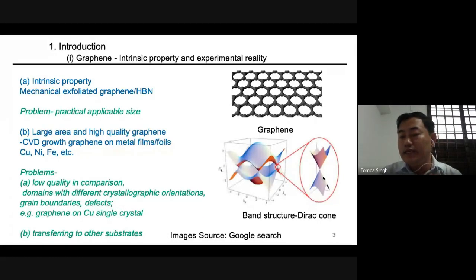Yes, the bands are linear, they follow the relativistic Dirac equation, so they are called Dirac electrons. The contact point is called the Dirac point, and the band is called the Dirac band. This is not similar to the usual materials which have parabolic bands. They follow the Schrodinger equation. Here it follows the Dirac equation. And there are 2 types of these corner K points, called K and K prime. They are different from the point of view of chirality.